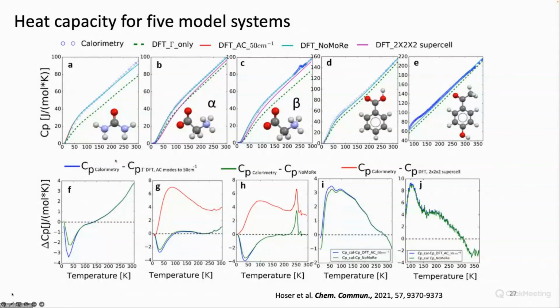You can see the calorimetric measurements are the blue open circles here, and if we compare that with the normal mode refinement model, that is the cyan curve here, you can see that that actually fits very well, much better than we had hoped for, I think. So we are quite happy with these results.